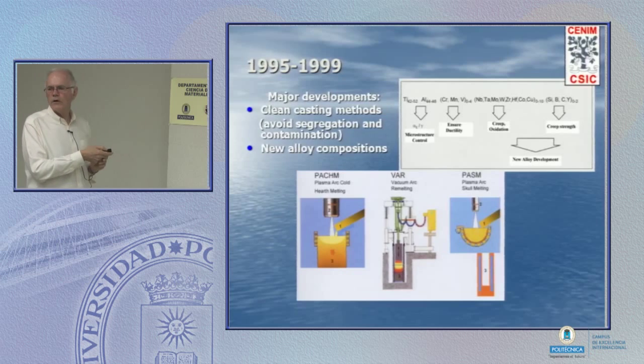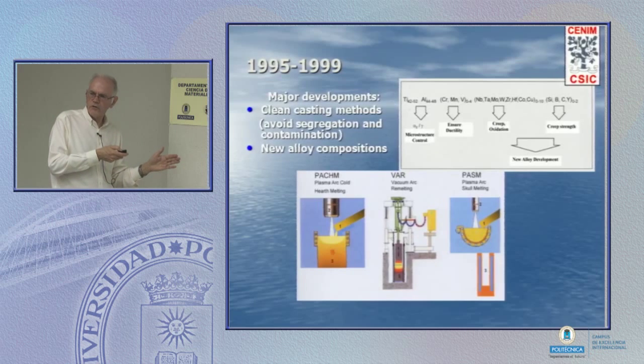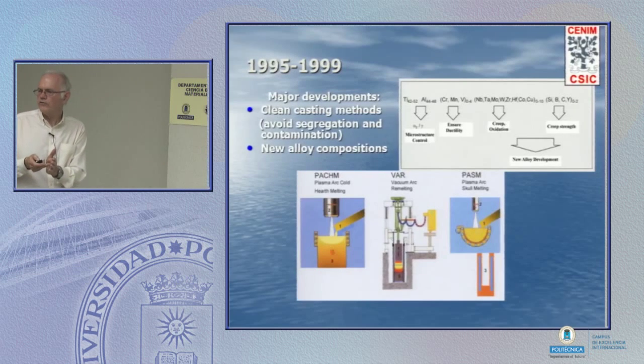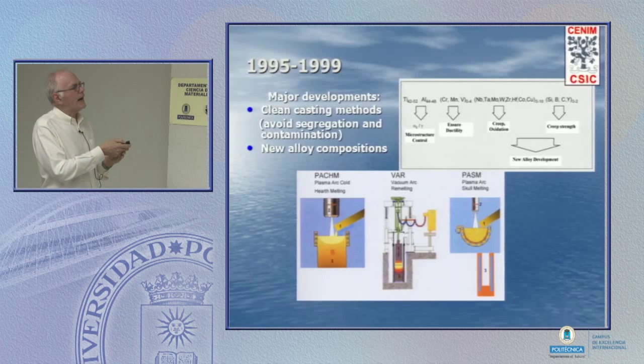And in terms of chemical composition, the balance of aluminum against titanium tells us how much of the Ti3Al, the alpha, and how much of TiAl, the gamma phase, we'll have in the mixture. And then adding chromium, manganese especially, we improve ductility.